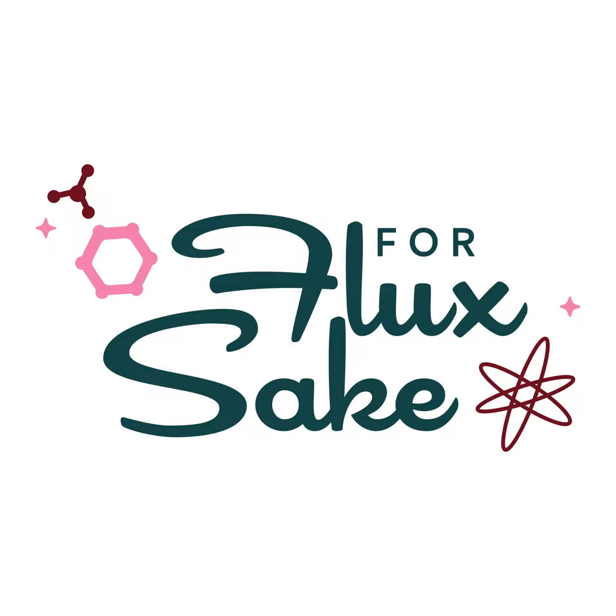So if you have a cone 6 recipe and it's got a frit in it, that's really to bring that temperature down. Frits, though, are using boron, and boron is actually a very rare element. Boron only has two major deposits in the world. One is in Turkey, and that's where a lot of Europeans and Asian folks will get their boron sources from. And the other one is in the United States in Southern California. There's a huge boron deposit, and that's where Gerstley borate originally came from.